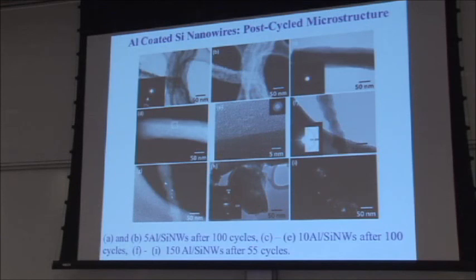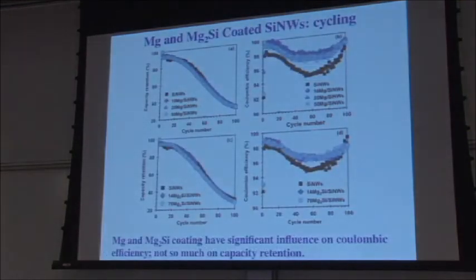So if the coating is thick enough, they separate, and essentially it's ships passing in the night. The silicon nanowires behave like silicon nanowires, and the aluminum behaves like aluminum. So there's kind of an optimum coating where these things keep, to enough of an extent, the nanowires intact. So the next two types of coatings we looked at were magnesium and magnesium silicide. And here we found absolutely no improvement in the performance, in the capacity retention.